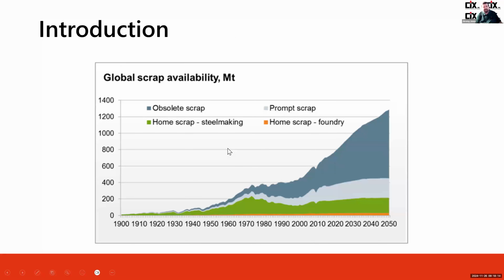Now, that being said, and I hear this argument a lot, oh, there's plenty of scrap available, it's not an issue, but is it the right scrap? And so what we see is that the projections for generation of home scrap are fairly flat going out into the future. Prompt scrap, a slight increase as we start to get higher grade products and manufacturing growing in the rest of the world. But what we see is that the obsolete scrap supply increases enormously. And the problem is that this is where we're seeing the steady rise in residual content, which makes it more and more difficult to utilize that material. So we have to come up with solutions, otherwise we'll be landfilling obsolete scrap.